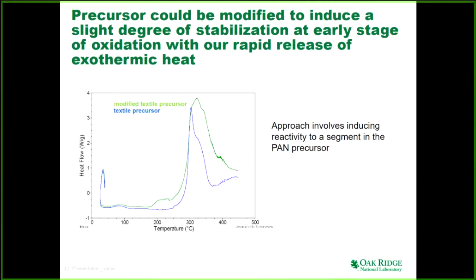So what we have done now, look at the green curve, we have done an induced reaction somewhere around 200 degrees Celsius, not rapid, but a slight, satellite-peak type exothermic peak, you can see that. So it is showing some degree of reaction there. So that's what we want. We want it to start kicking in the reaction at an early stage. That is good, but you don't want it to be so vigorously evolving heat that it will melt or shrink too much. So that's what we have exactly devised.